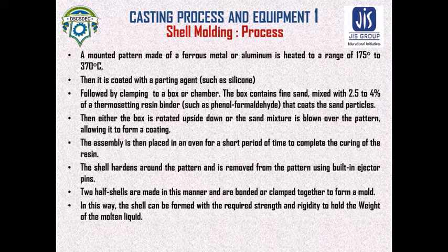It is clamped in a box or chamber. Then the box contains fine sand mixed with 2.5 to 4% of thermosetting resin binders, and that coats the sand particle. That means the box contains coated sand.